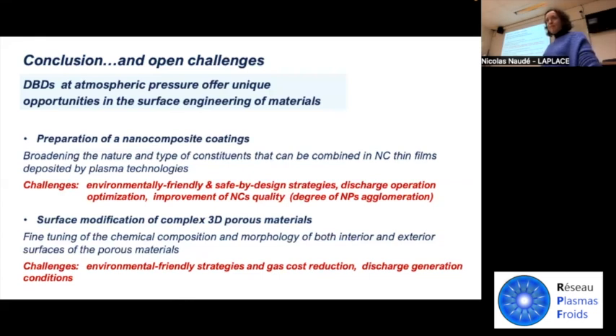You mentioned the adhesion on the sample is mainly controlled by the polymer matrix. What about the role of the nanoparticles on the adhesion? And is there some change, as mentioned by Richard, along your material, outside or inside? In principle, regarding the mechanical properties of these coatings, since they are very porous and the matrix is just a hydrocarbon coating, they are in principle very, very soft.